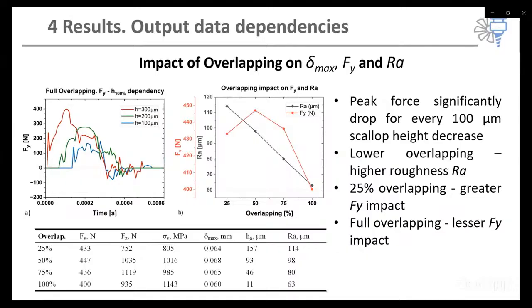Considering the graph on the left, it is noticed that with every 100 microns decrease in scallop height, the horizontal force Fy drops significantly. What can be estimated from the graph on the right? As the degree of scallops overlapping increases from 25 to 100%, the surface roughness decreases from 114 to 63 microns, indicating the residual scallop becomes smaller. Generally, the lower the overlapping, the higher the roughness. The higher the overlapping, the lower the force impact on the wall.